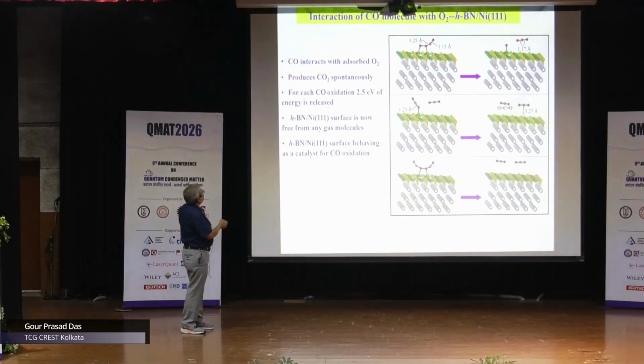Very interesting. Now we try to bring a carbon monoxide. This is the carbon monoxide. And this is oxygen, which I already showed you. And this is elongated, it is activated. Now this carbon monoxide comes and takes up one oxygen and becomes a CO2 and goes away. The remaining oxygen, which remains here, the next CO comes, takes out the oxygen, and both the CO2s go out, and what remains is a pristine hexagonal boron nitride on nickel 111. This is a glaring example of oxidative catalysis.